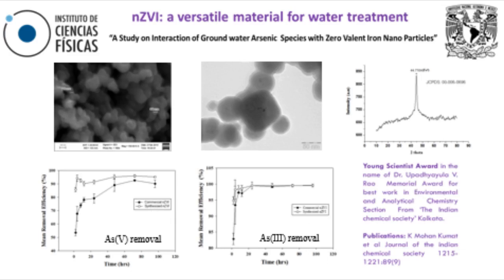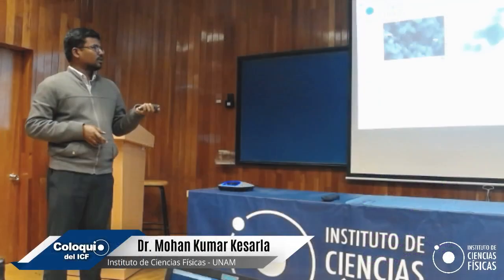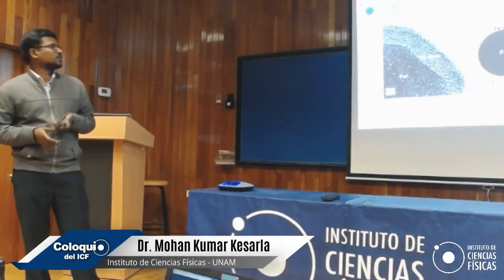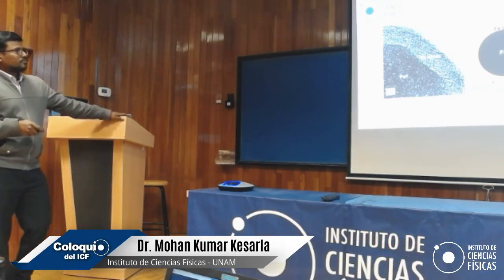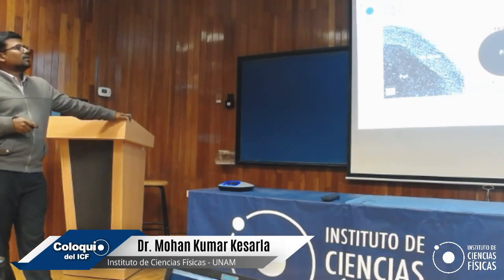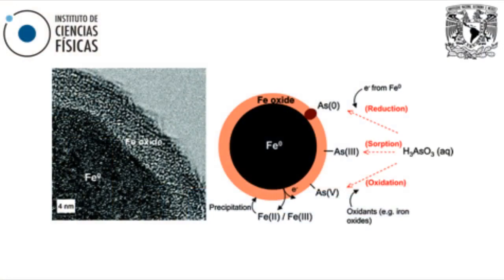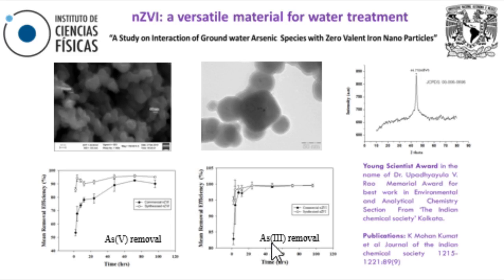So what's the reason? Actually, this is the work for which I got the award from the Indian Chemical Society. Here, if it is arsenic 5, it will directly adsorb onto the surface. If it is arsenic 3, it will first oxidize to arsenic 5, and then adsorption will take place. So that's why, if you look at these graphs, you have the difference in adsorption capacities of this zero valent iron.